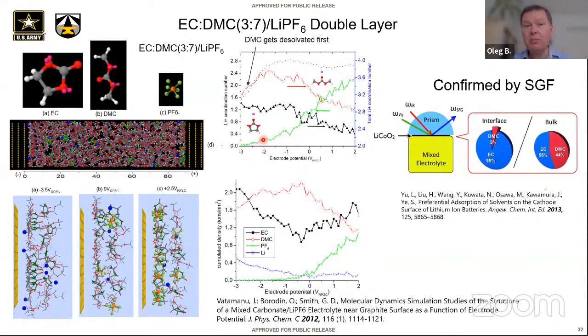Now let's look at the same, but in a quantitative way. First, we are looking at the lithium coordination number. That's a very DMC-rich electrolyte. So DMC is present in higher numbers, despite EC having a higher preference to coordinate lithium. What happens as we polarize it negatively, we see that EC pretty much stays. Lithium starts losing PF6, right? It doesn't want to have as much PF6, and that's different from what we observe in